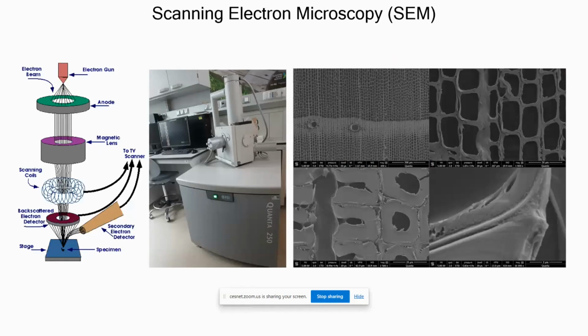Another technique we tried to apply on this wood is scanning electron microscopy. In this case, it's even more challenging because normally for this kind of sample preparation, we trim the surface of a small cube of wood to make a very flat and nice surface. Then we coat the wood to make it conductive, in this case with gold, and then we can observe it.